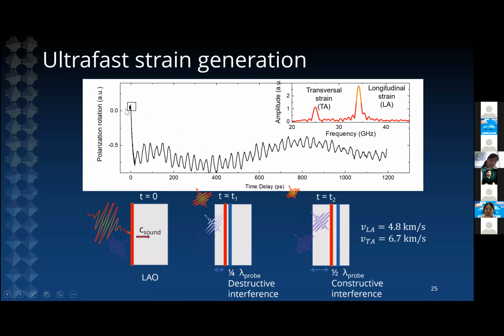So this is another measurement performed in our lab of polarization rotation as a function of time, and you see this pattern of oscillations with a frequency in the gigahertz range. So the origin of these oscillations is, as I was saying before, we have an extinction depth of this mid-IR pulse that is penetrating at resonance a few hundreds of nanometers at the surface of the material. The material is experiencing a large electric field and therefore an expansion of its lattice parameter, and this generates a strain wave that propagates through the material at the speed of sound. And as our probe pulse comes, the probe pulse experiences destructive and constructive interference with the pulse reflected from the pristine surface of the material as it interacts with this moving phase front.